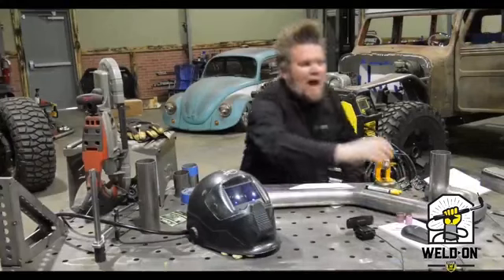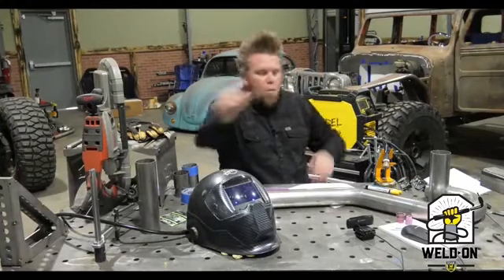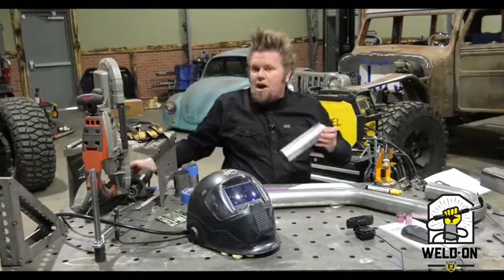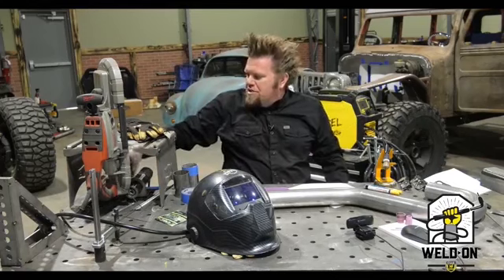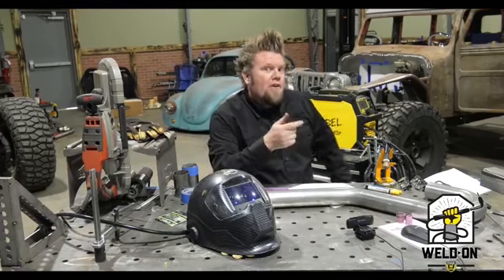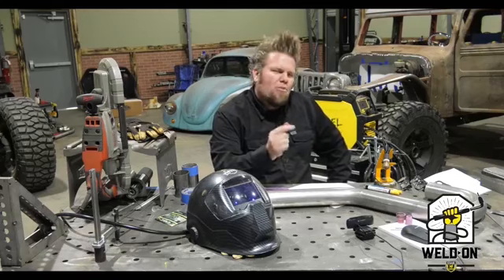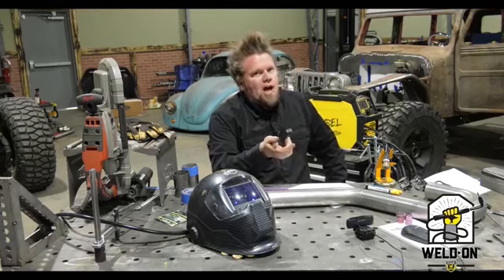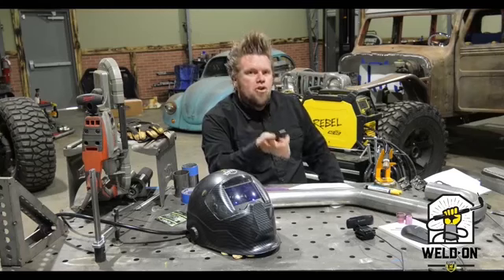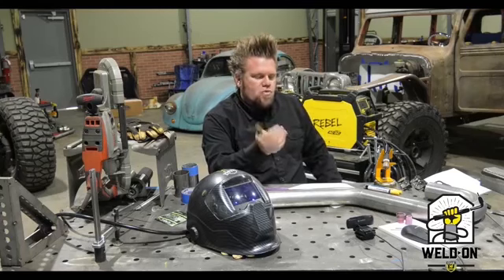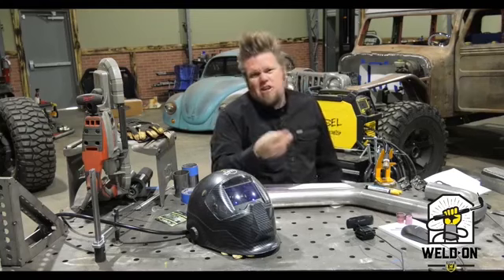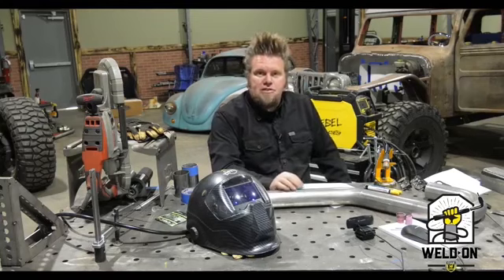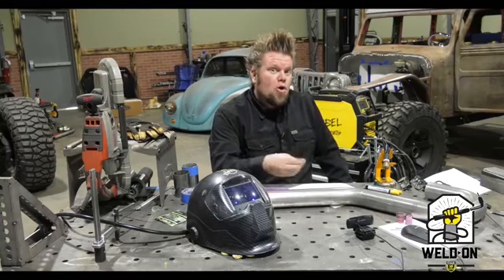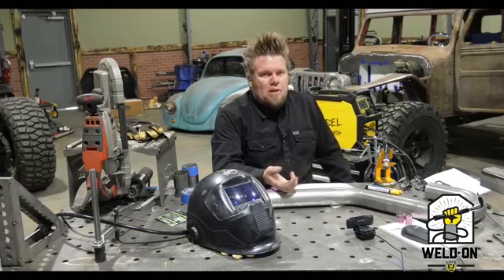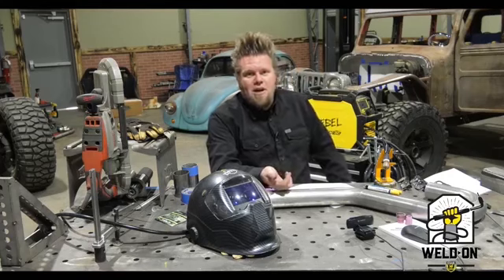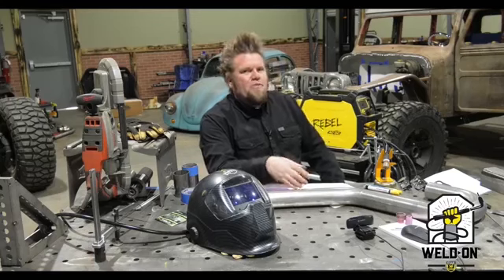Now, why that is bad is because that's going to affect it when we weld it together. That's going to cause some impurities in the weld, and a not very good looking weld. Those impurities will boil up to the surface, and that can quite often cause that weld to gray out prematurely. Graying out on a stainless weld, especially on exhaust, there are lots of reasons why it grays out, but that's basically the chromium boiling out. There are some structural issues there, but not so much when we're talking about exhaust. It's more of an appearance issue.